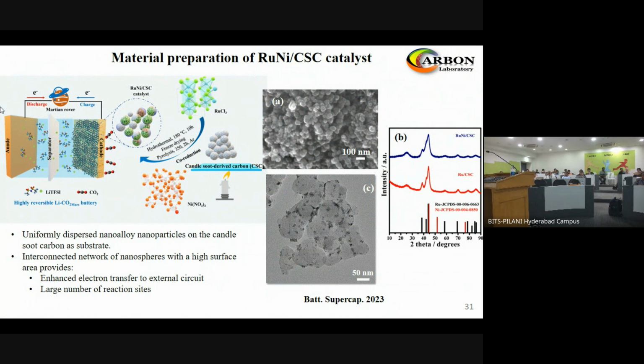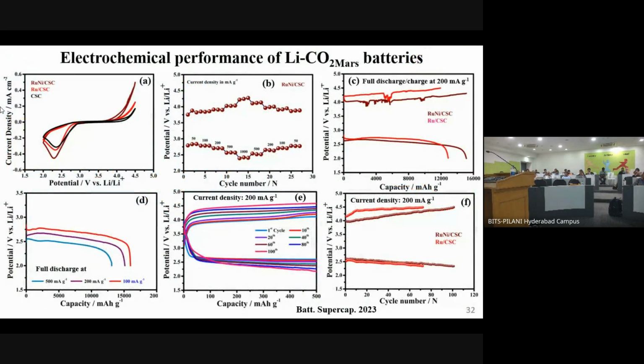So basically the interconnected network of the candle soot nanoparticles with the high surface area is providing more enhanced electron transfer to the external circuit, and that also provides a large number of reactive sites available for the CO2 redox reaction. And this is how the electrochemical performance goes. So we can see the ruthenium nickel candle soot carbon gives a much higher current response as compared to two other systems, only candle soot and ruthenium candle soot.